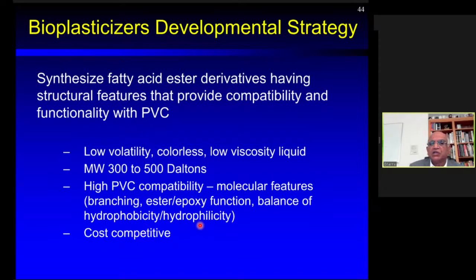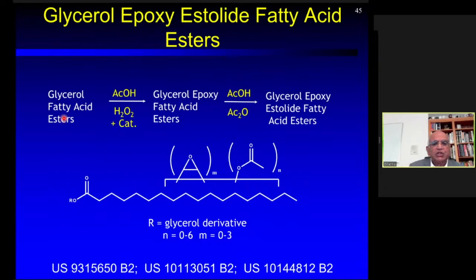They are the glycerol epoxy estolide fatty acid esters, and the synthesis of which is shown here. We took the glycerol fatty acid esters and converted them to the epoxides by reacting with hydrogen peroxide in the presence of a catalyst. Those epoxide groups are partially ring opened with acetic acid and converted to the acetyl derivatives called estolides on the acyl chain. So these are the glycerol epoxy estolide fatty acid esters that were tested as plasticizers. Our partners, Evonik and BASF, were the ones who evaluated them as bioplasticizers, and they found the properties shown here.